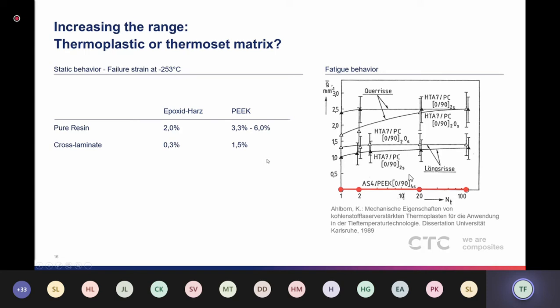This helps with the creation of micro cracks due to the CTE mismatch of fibers and resin, and also with the impact behavior. We can see here a trial where a PEEK specimen was subjected to cryogenic hydrogen, and after 100 cycles of subjecting it to it, there was no crack yet observable in the PEEK.